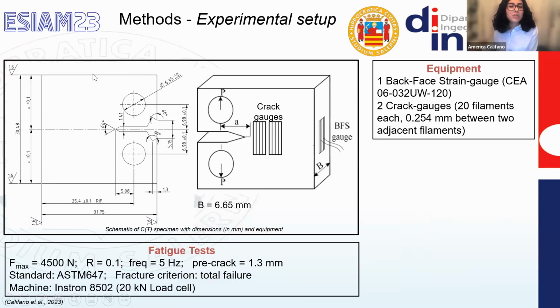As a matter of fact, here you can see a schematic of the CT specimen with the dimensions expressed in millimeters, while on the right, a simplified schematization of an instrumented specimen. Each CT specimen was instrumented with 2 crack gauges, characterized by 20 filaments each, and with a distance of 0.254 millimeters between 2 adjacent filaments. And then a back face strain gauge was glued as well on the face that is opposite of the face on which the notch was introduced.